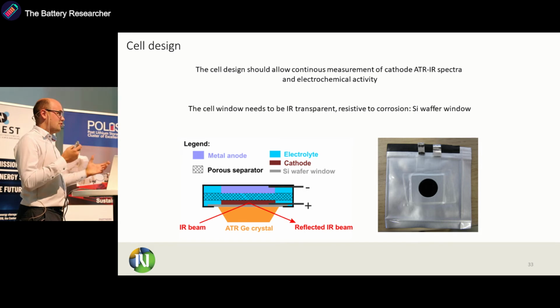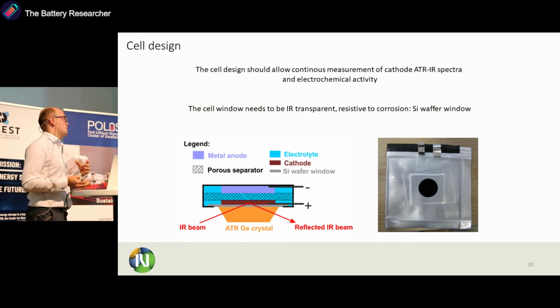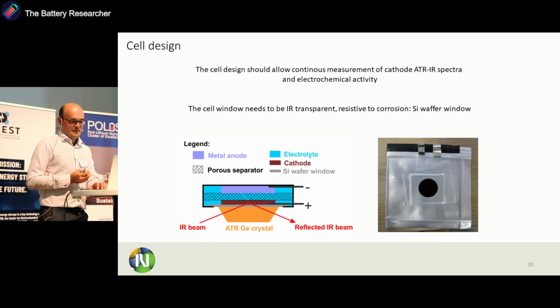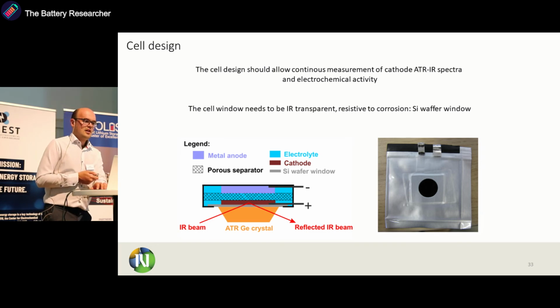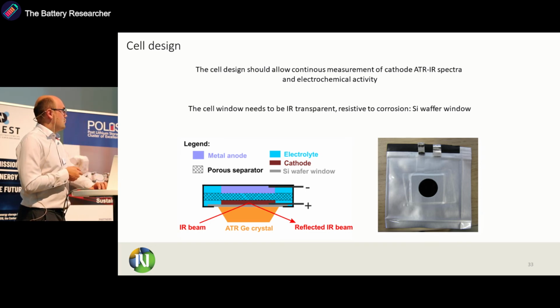We wanted to measure infrared spectroscopy also during the cycling, not just ex situ, where you have issues with stability of the samples and also washing them and not being sure if they decompose in between. So we wanted a cell that will allow electrochemistry and at the same time also ATR infrared measurements. So we decided to put a silicon wafer window into the pouch cell, and we got something like this. We have the ATR crystal, we put on the silicon wafer, and then on the other side we have the cathode, and we basically probe from the back side.